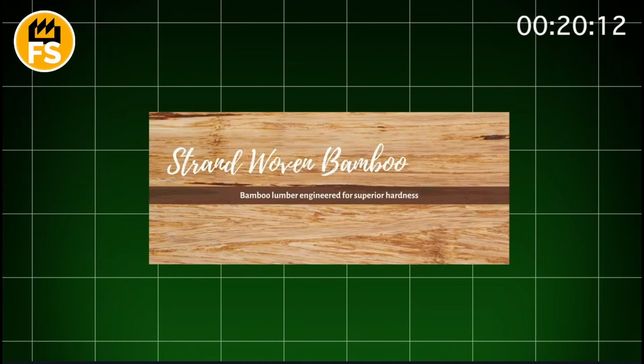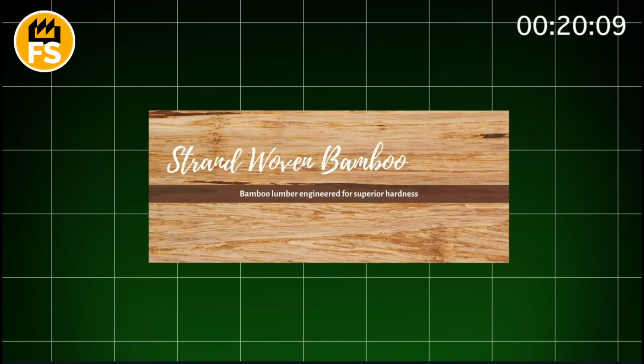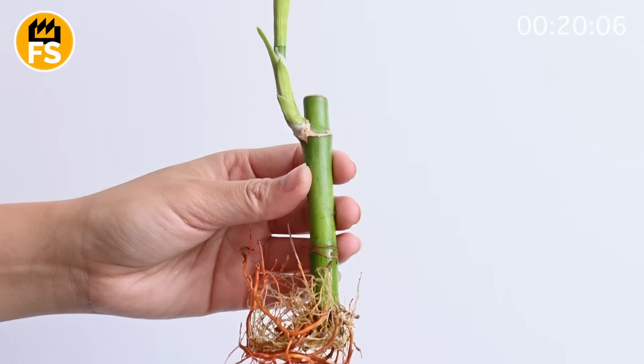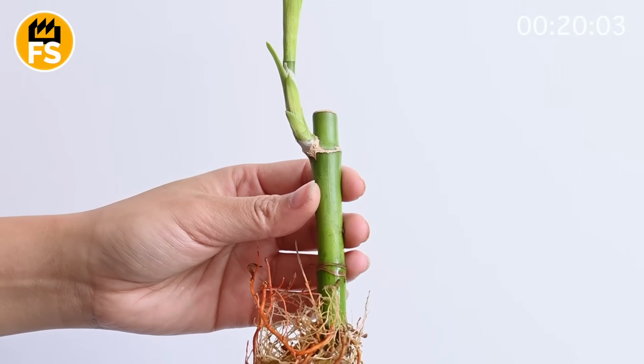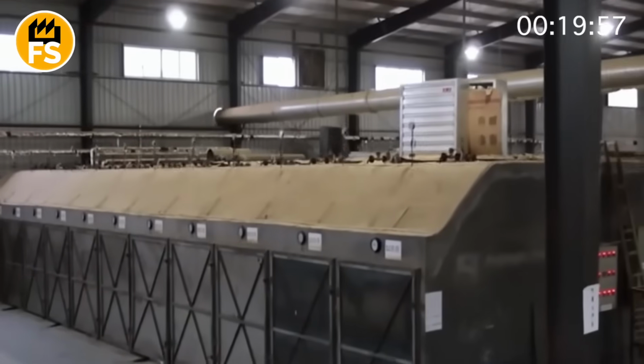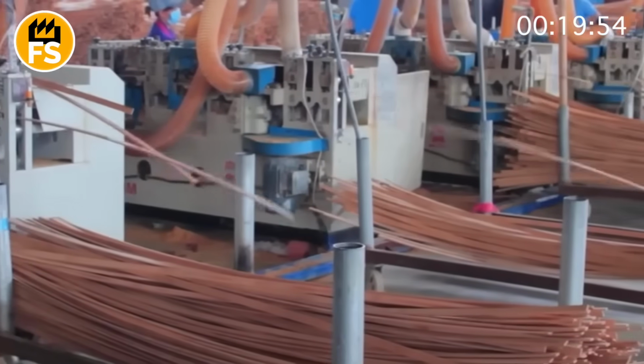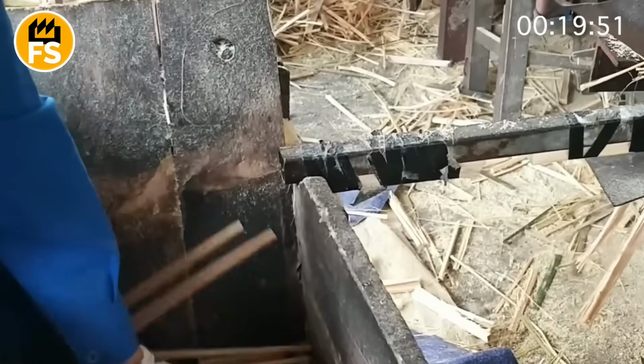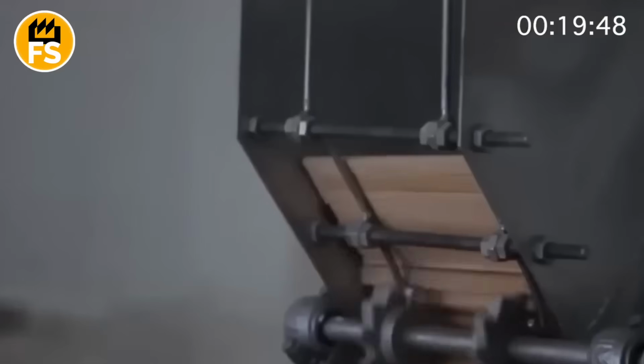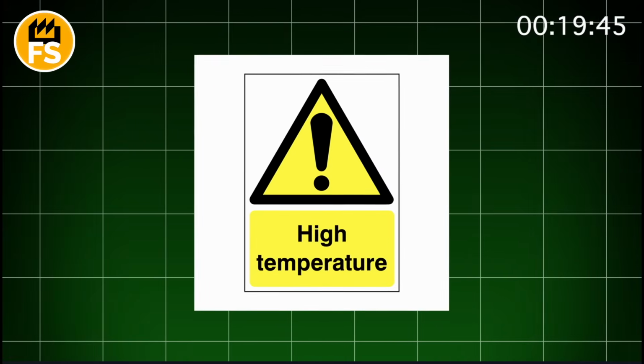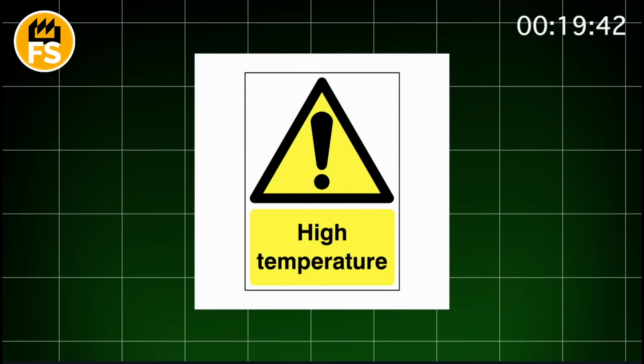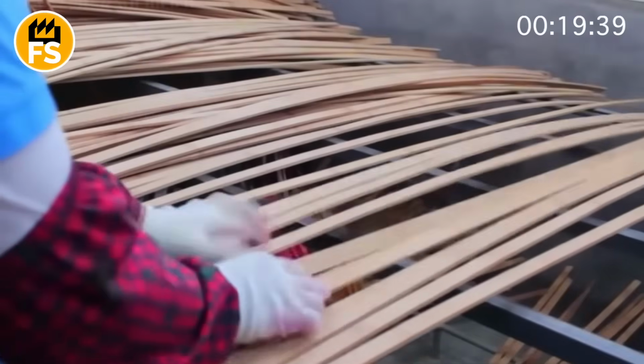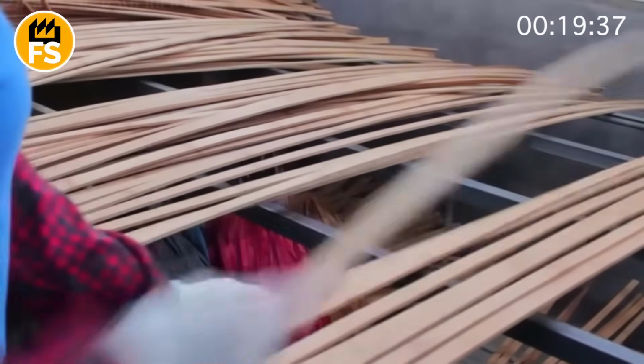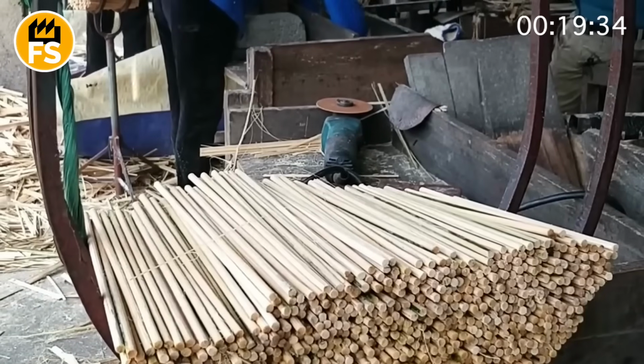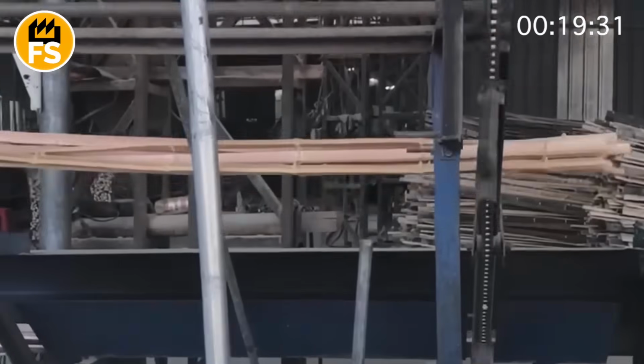But the real marvel is the strand-woven technology. Here, the bamboo planks are not just glued together, but completely shredded into long fibers, mixed with an environmentally friendly resin, and loaded into huge steel presses. Under infernal pressure, reaching 3,000 pounds per square inch, and high temperature, this mass transforms into an extremely dense, monolithic block. The hardness of such flooring on the Janka scale can exceed 5,000 units, making it more than 3 times harder than oak, and more resistant to scratches and dents than most traditional wood species.